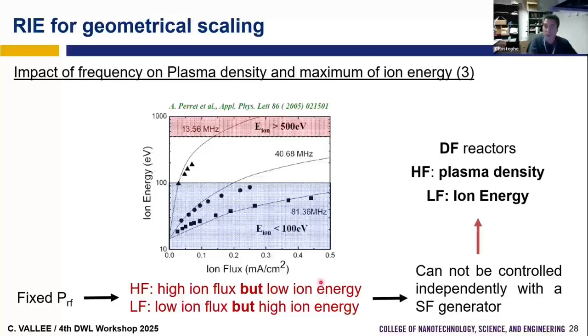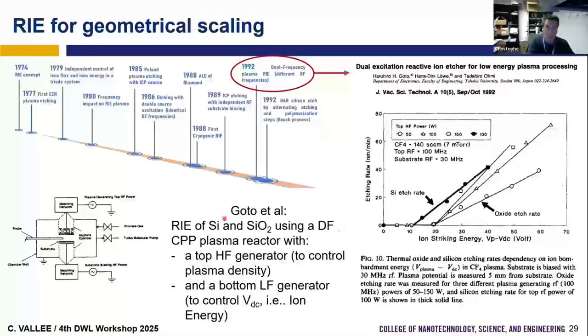So the idea is that maybe we can use a CCP and we can have two different generators, where we have a high frequency generator and we use the high frequency generator to control the plasma density, so the ion flux. And we have the low frequency generator to control the ion energy. So this is what we have.